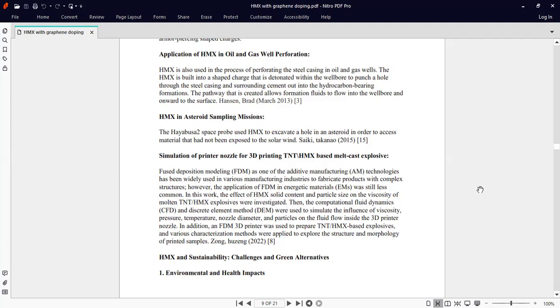In this work, the effect of high melting explosive solid content and particle size on the viscosity of molten TNT HMX explosive were investigated. Then the computational fluid dynamics, CFD, and discrete element method, DEM, were used to simulate the influence of viscosity, pressure, temperature, nozzle diameter, and particles on the fluid flow inside the 3D printer nozzle. In addition, an FDM 3D printer was used to prepare TNT HMX based explosive and various characterization methods were applied to explore the structure and morphology of the printed samples.